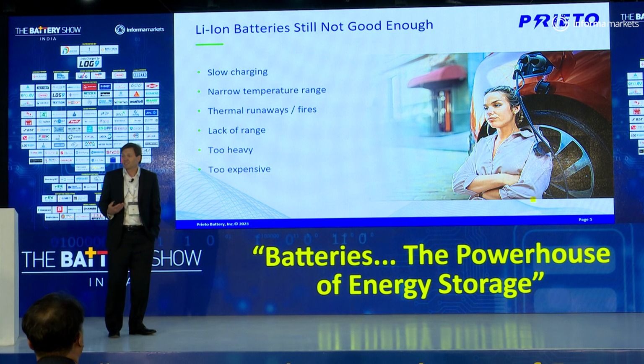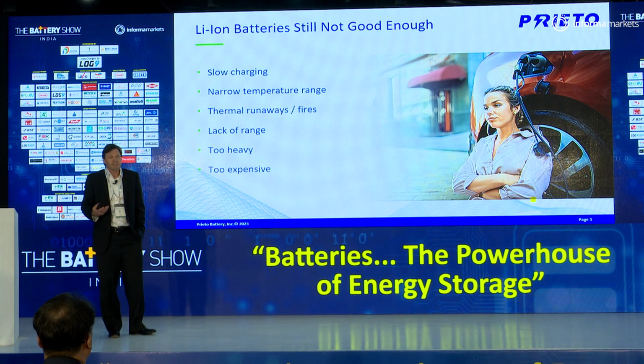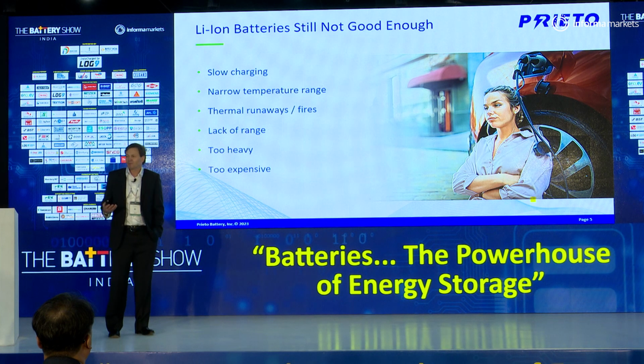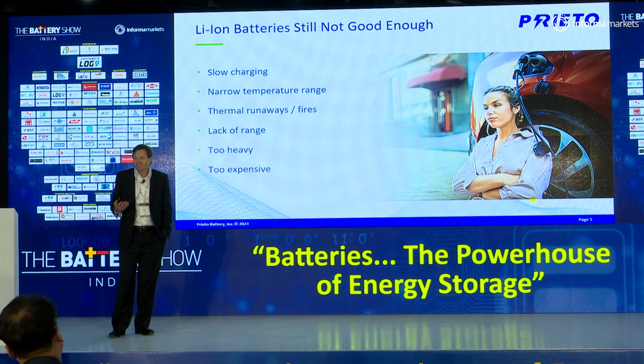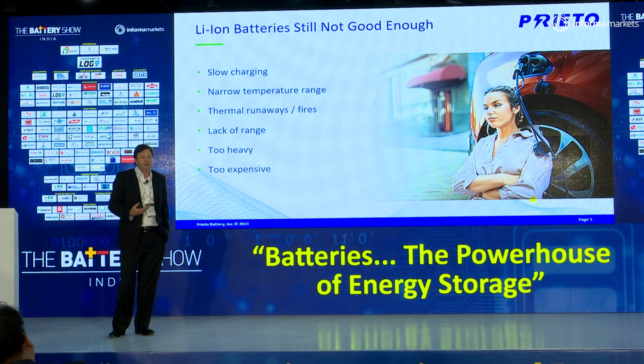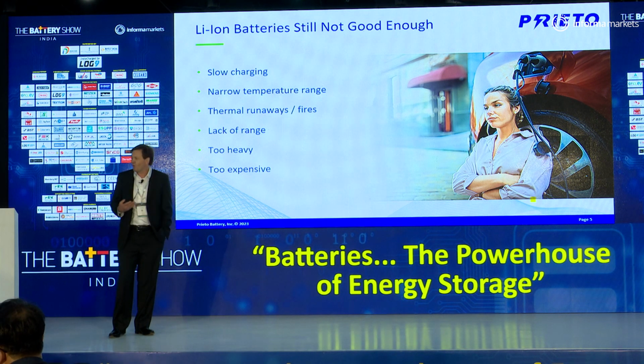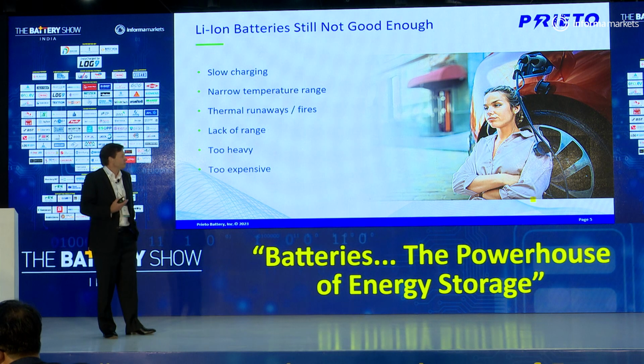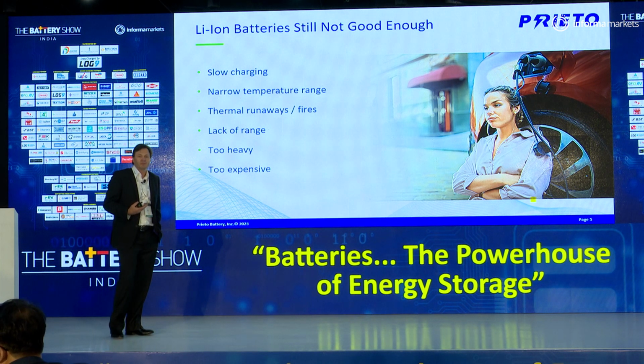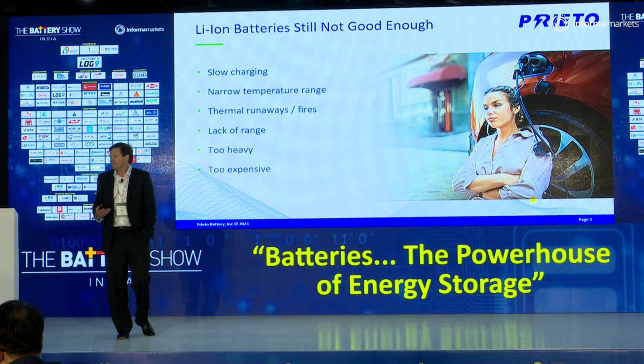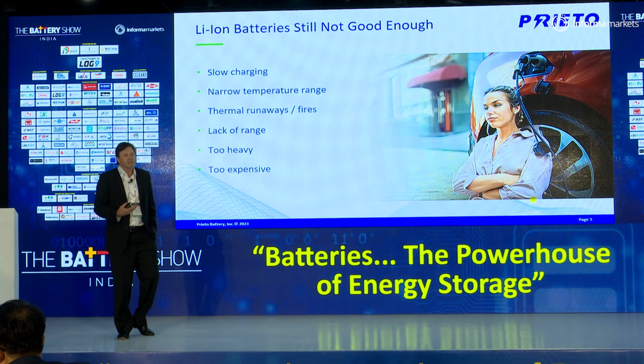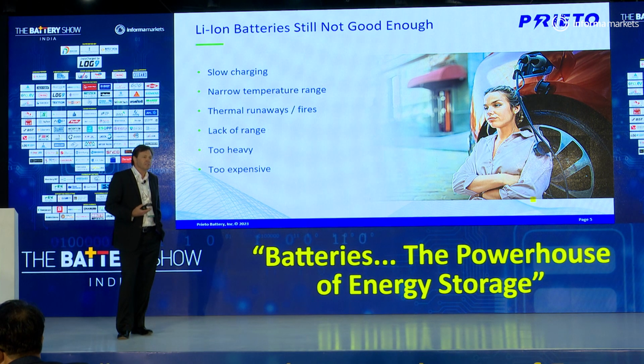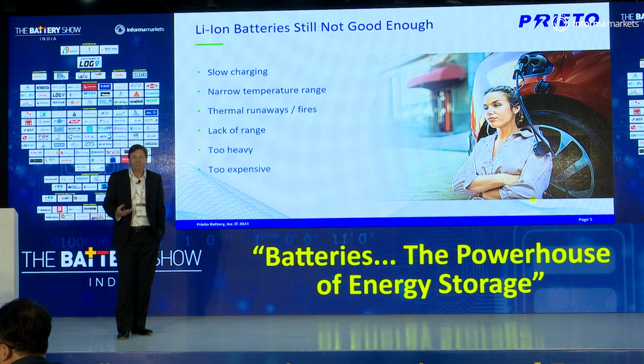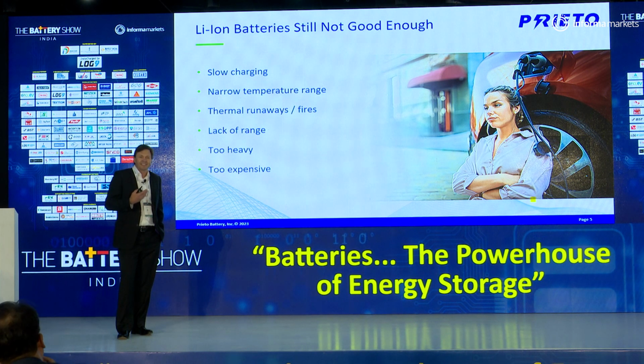India has very high temperatures, 55 degrees C. That's going to require battery temperatures going up to 80 degrees C. How does that work with a traditional lithium-ion battery? It doesn't. You need something with a wider temperature range. Thermal runaway fires are still a problem. We just saw a presentation talking about how to keep fire from happening. That needs to be resolved. These batteries lack range, they're heavy, and they're too expensive. So to get into the Indian market, you need a battery that can address these issues.